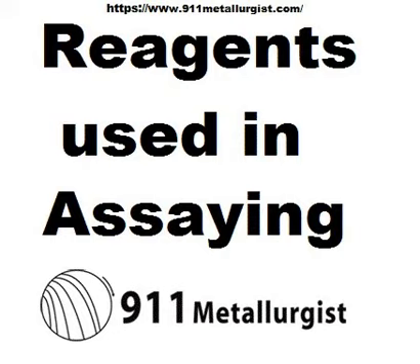Copper, Cu — pure copper, as obtained by electrolysis, can be purchased; this only should be used. Copper oxide, CuO, occurs as a black, heavy, and gritty powder, and is used for the oxidation of carbon and hydrogen in organic substances. It should be ignited and cooled out of contact with air just before using, since it is hygroscopic. Oxide of copper which has been used may be again utilised after calcination. Copper sulphate, CuSO4·5H2O, contains 25.4% of copper. The recrystallised and pure salt is used for preparing the anhydrous sulphate, which is used for detecting moisture in gases; it is dried at 200 degrees centigrade till no trace of green or blue colour remains. Traces of moisture develop a green colour.